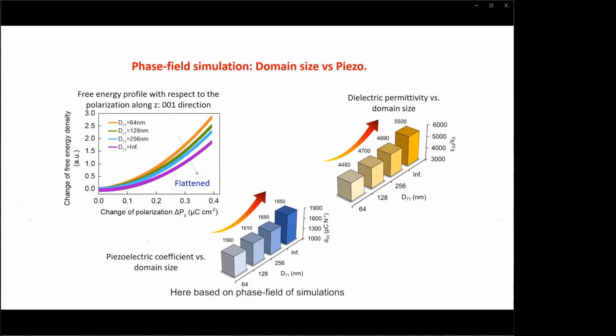Here, based on phase field simulations, we certified that a larger domain size of rhombohedral PMN-PT crystal can result in a higher piezoelectricity. But we'd like to note here that for ferroelectric crystals, the relationship between the domain size and the piezoelectricity is related to many factors. For example, the symmetry of ferroelectric phase, the composition of the material, and also the poling direction. The domain size dependence of other ferroelectric crystals could be different from that observed in PMN-PT crystals.